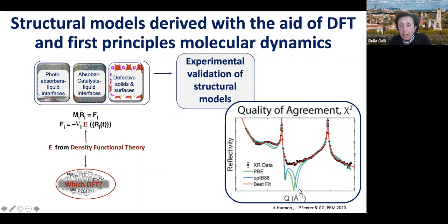And the two curves here represent two different functionals. So you see, we have a good qualitative agreement. We get the main peaks, and the region here where there is some disagreement is a region of very low density, but the quantitative agreement is not perfect, and you have to keep it in mind when you interpret your results, and it's not the same for different functionals. There is no one-size-fits-all when it comes to validation.